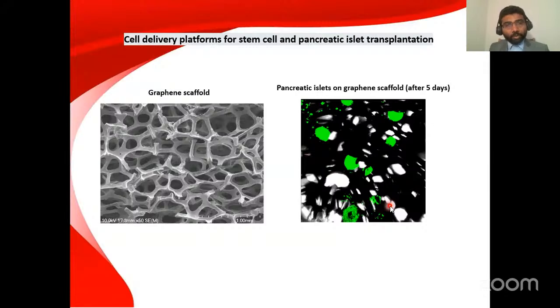Also, at Stanford University, as I mentioned, I have limitations in telling all these intellectual property related things. However, we are doing pancreatic islet transplantation kind of research, which is very clinically relevant. We are also helping clinical teams to develop biomaterial scaffolds. In one such study, we developed graphene scaffolds. This is a pure graphene scaffold without any polymer, just graphene. We made it as a highly porous structure using a special CVD approach, using a template.